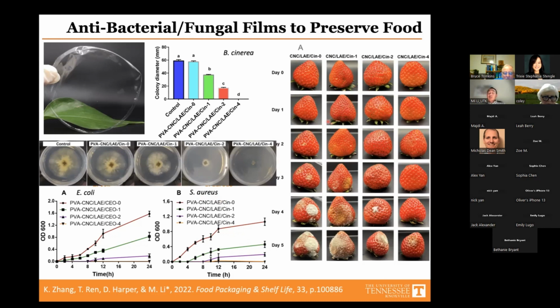So finally, to the right, we apply this package, the film, to cover these strawberries, and we then look at them to measure the decay of the fungi. On different days, from 0 until 5 days, and with different concentrations of the emulsion incorporated in the film. And it turned out with the 1%, 2%, 4%, they all show pretty good improvement of the shelf life of the strawberry. Okay, that's the first story.